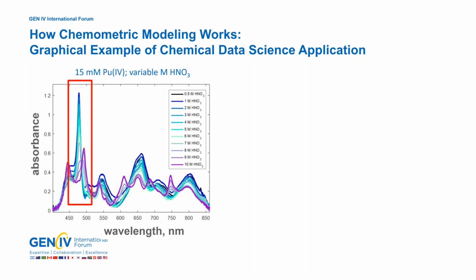What we're looking at here is UV-vis absorbance spectra of pretty much that same chemical system, what we would still consider a very simplistic chemical system. It's got nothing except plutonium-4 and nitric acid in here, except this time we've cut the deck a little bit differently. In this case, we're holding that plutonium-4 constant now at 15 millimolar, and we're varying our nitric acid from 0.5 molar all the way up to 10 molar. And what we see here is a drastic change in that plutonium-4 fingerprint.